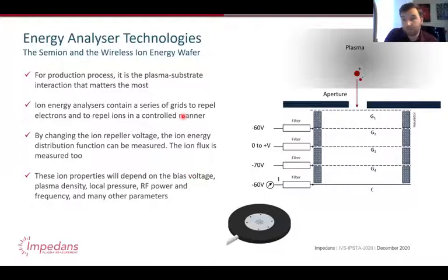There are these things called retarding field energy analyzers, and they're constructed something like this. They have a very small dimension, usually sub-millimeter or a couple of millimeters, because you don't want any collisions inside the analyzer. Essentially you have a series of metal grids with different voltages on them. On one of the grids, you vary the voltage to block ions. When there's no blocking voltage, you collect all the current. At some point, you block all the ions coming in. And in between, you get information on the ion energy distribution function.